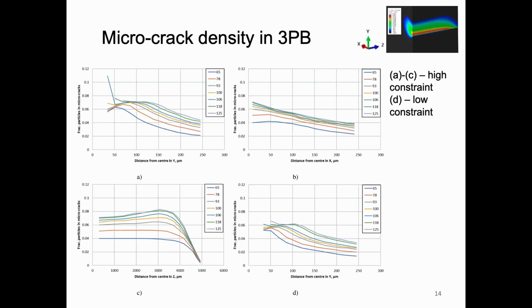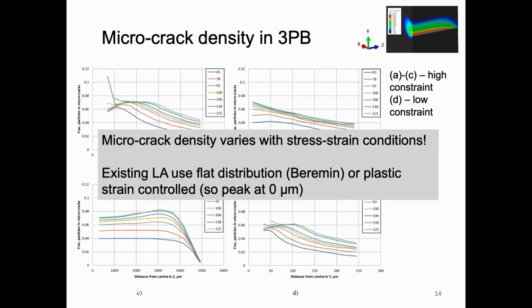You can see that microcrack density varies with stress strain conditions. And that is contradicting the existing local approaches, where this distribution is constant. You are assuming that the microcrack distribution is exactly the same everywhere. So that is one of the problems. There are models where the microcrack distribution is controlled by plastic strain, but it follows the plastic strain distribution, which means the peak is infinite in an elastic plastic material. So this is one of the things that we found with the model.